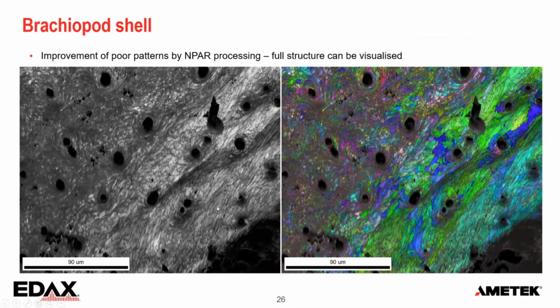So the contrast in the IQ map really improves. That means that the patterns inside the grains are better. So the bands are stronger in the band detection, which is what gives me this brightness in the grains. And at grain boundaries, we still have poor patterns. So the difference between the edges and the grain interiors is increasing.